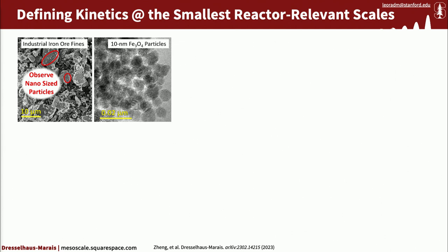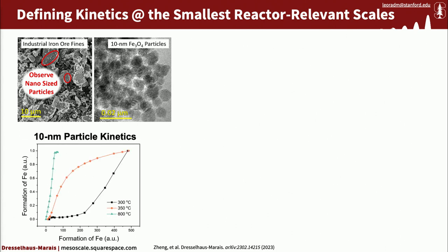And we very quickly found that when you look at these under a scanning electron microscope, there are a lot of features and grains that are sub 10 nanometers in scale. As material scientists, we know that nanochemistry in these types of particles is not the same as the macroscopic chemistry that we typically would use to describe a reactor at this scale. So we generated these 10 nanometer particles to be able to look at the process at the relevant length scale, a scale that's always been overlooked so far.